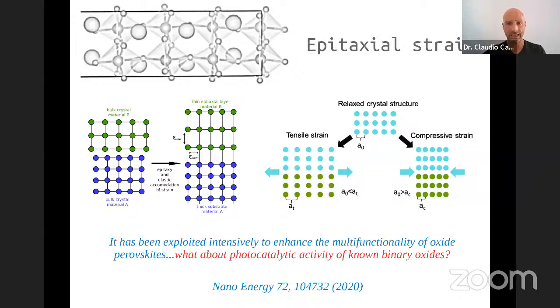And depending on the lattice parameter mismatch between the thin film and the substrate, it is possible to introduce either a tensile strain or a compressive strain on the material, right? The strain, of course, acts in the plane of the interface between the two materials, the substrate and the thin film, right? So this first work tried to answer: what about using this kind of strategy for improving the photocatalytic activity of known simple oxide materials, right? Which are the typical materials that one finds in this context of photocatalysis.